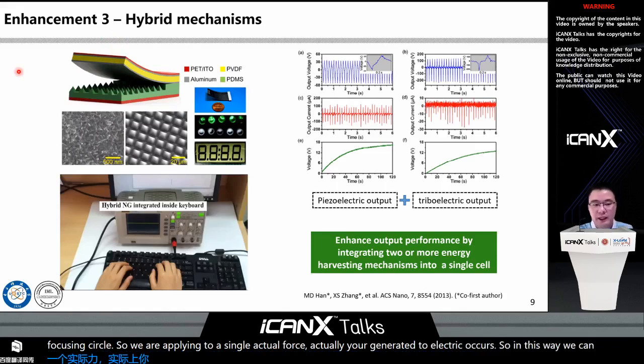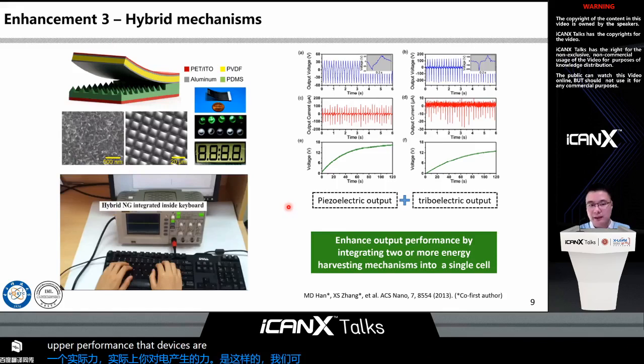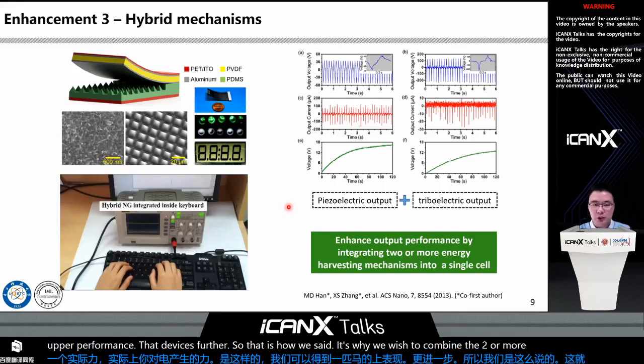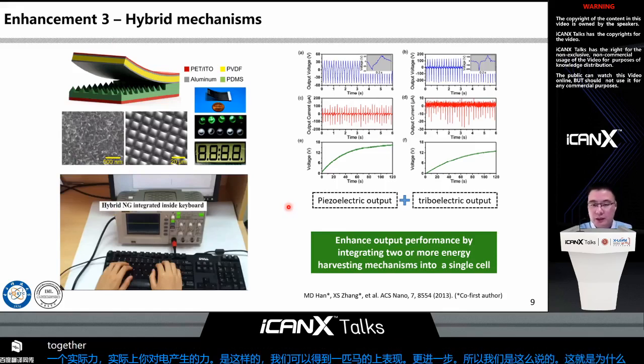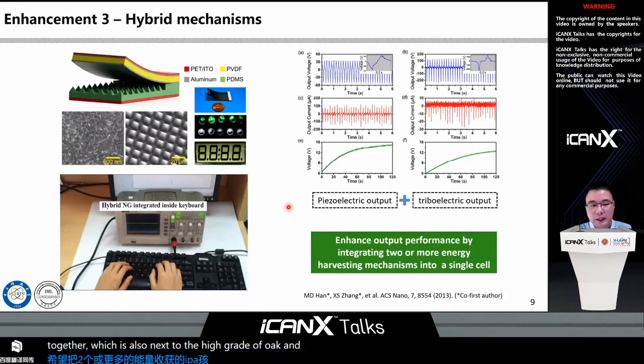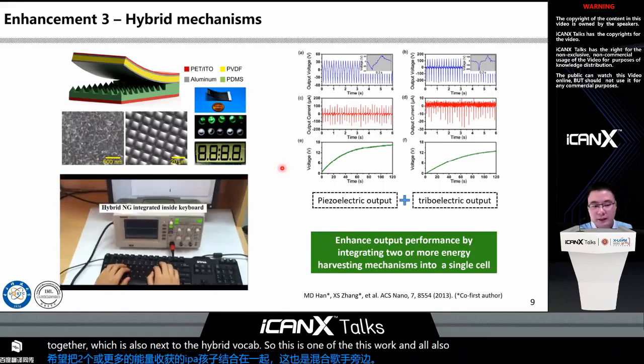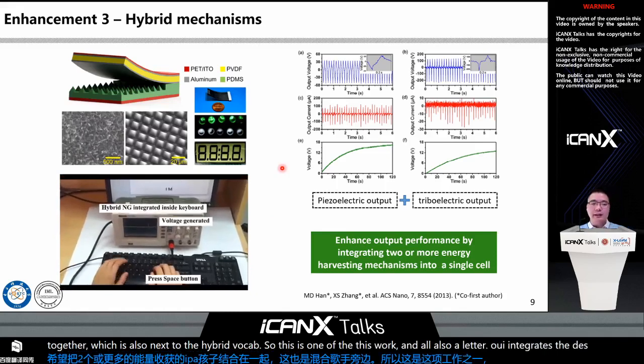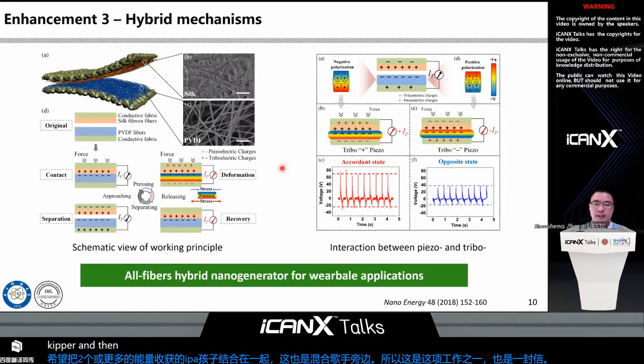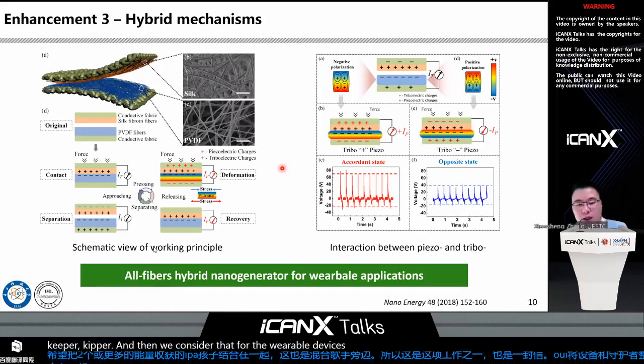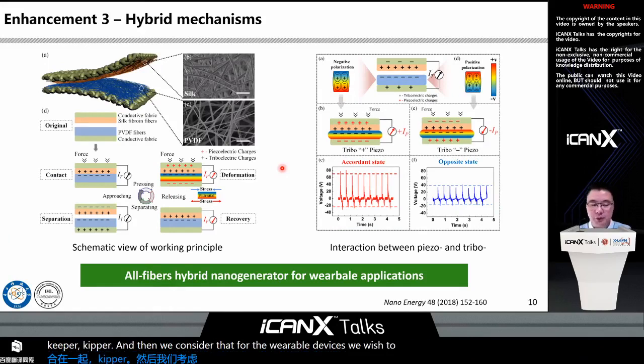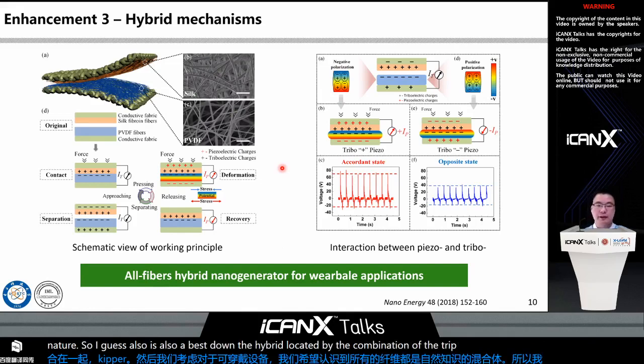That is why we wish to combine two or more energy harvesting mechanisms together, which is also named the hybrid mechanism. This is one of our works. Later, we integrated the device with a keyboard. And then we considered that for wearable devices, we wish to realize an all-fiber hybrid nanogenerator. It is also based on the hybrid mechanism, by the combination of the triboelectrification effect and the piezoelectric effect. Here you can see there are two conductive fabrics.